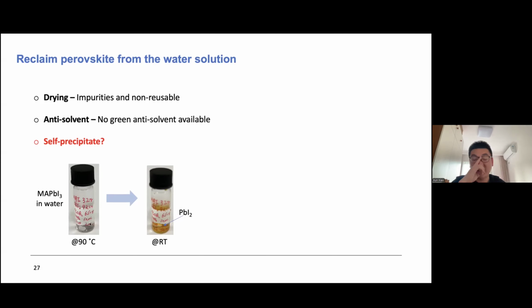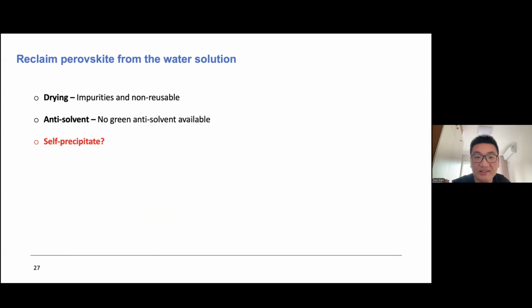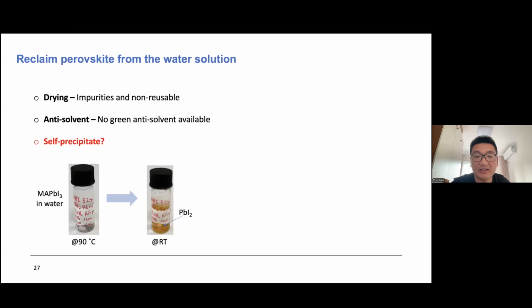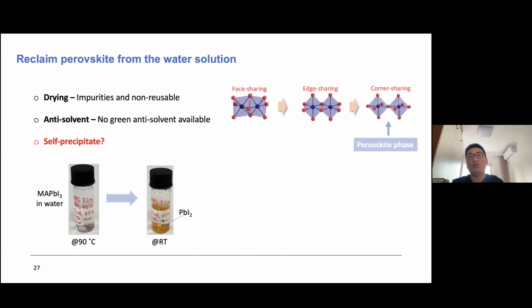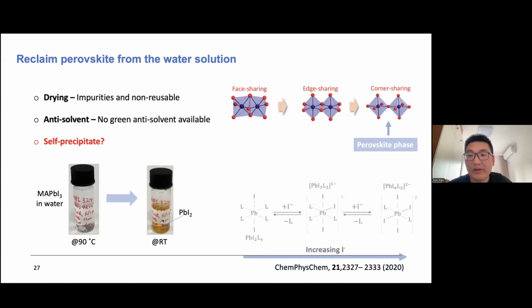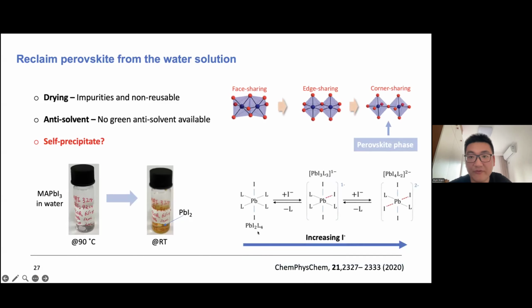Then we can get the crystals. It's very naive thinking at the beginning. But when we tried to do this, we found that even if we combine these two additives, the sodium acetate and the reductant, we still get the lead iodide precipitates. It's not the perovskite that we want. So then we were thinking, what's wrong with it? We searched the literature. We found actually the lead ions, the lead iodide, have this edge-sharing structure in the solution.